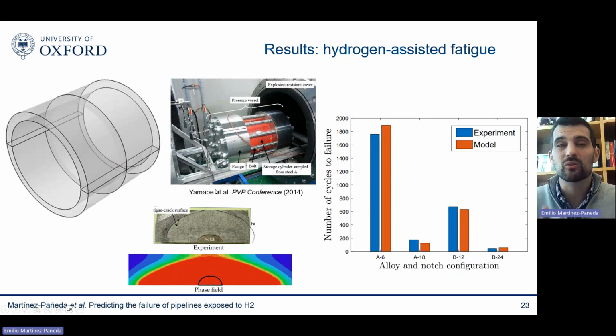And more excitingly, we can also do things not only at the lab scale, but also at the full scale, right? We can benchmark our model against full-scale samples. So this is a comparison with some full-scale fatigue tests done on pressure vessels, where they consider 2 types of alloys and 2 types of defects in those pressure vessels. And as you can see, we get, again, a remarkable agreement in terms of cycles to failure. So we can simulate the pressure vessel in 3D. We can emulate exactly the conditions of the experiment. And as you can see, we get very nice agreement in terms of the number of cycles to failure across different materials and different notch geometries.